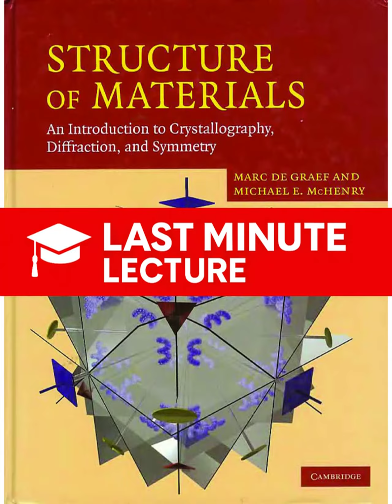But that rotation stops at lower temperatures. Below 249 Kelvin, the spinning ceases and the molecules lock into a specific orientation, and the structure transforms to a less symmetric, primitive cubic structure. It's a classic order-disorder phase transition. And C70, which is slightly elongated like a rugby ball instead of a perfect sphere, crystallizes differently. It does. At room temperature, it forms a hexagonal close-packed, or HCP, structure. It's a great example of how a tiny change in the molecular geometry dictates the entire bulk crystal arrangement.